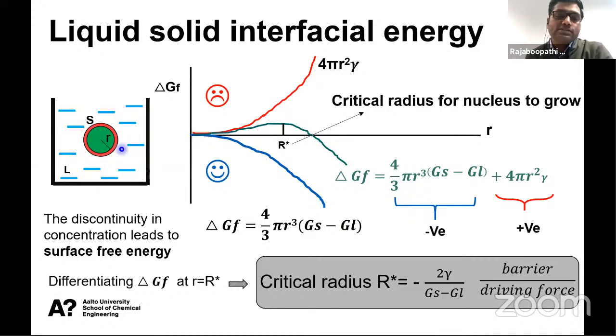After forming the nucleation cluster, there is an interfacial energy between the solid and the liquid. Liquid means supersaturated solution. The interfacial energy is a kind of external energy which suppresses crystal growth. You can assume that the interfacial energy is a kind of surface tension in the liquid. Since it is suppressing the growth, the Gibbs free energy of the system will increase. So we should reduce the Gibbs surface free energy to grow bulk crystals, or to get a nucleus from the nucleation cluster. So this is the total Gibbs free energy change.